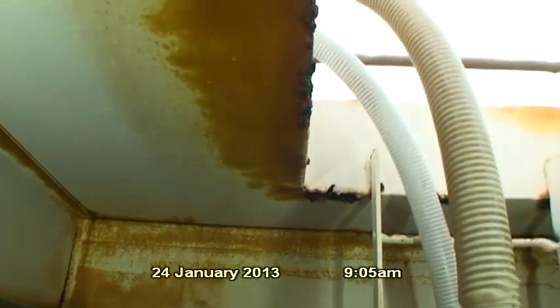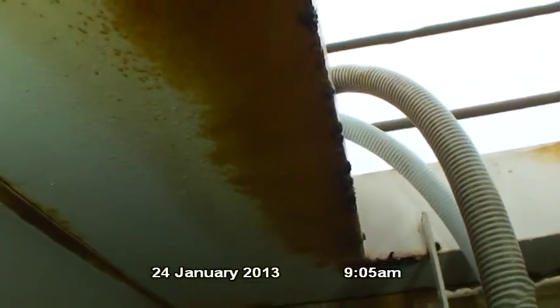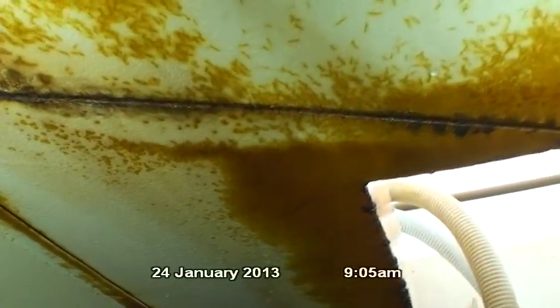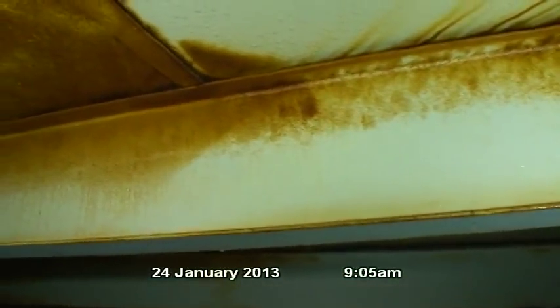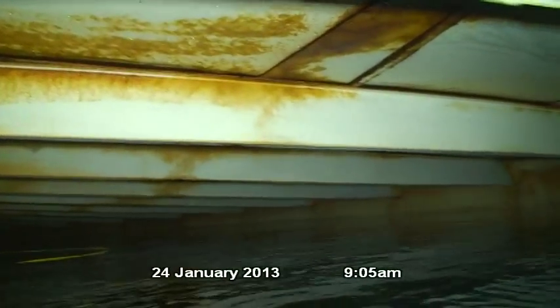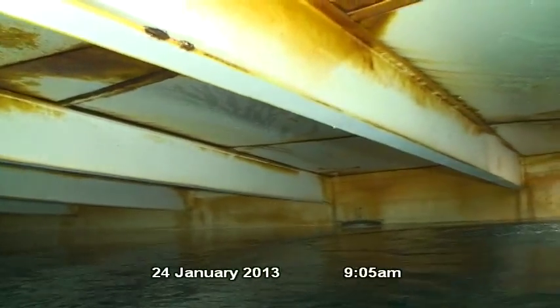We're now going to document the above water portion of the facility. The roof structure is coated with epoxy. The condition of the epoxy coating ranges from good to poor. Corrosion is present in many areas on rafters and roof plates. Moderate corrosion is present on the edge of a few rafters. Slight metal loss appears to be taking place where moderate corrosion is located. Light to moderate corrosion is present on tie rods in a few areas.